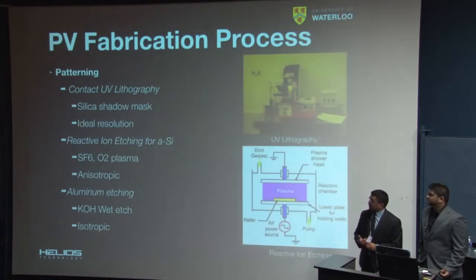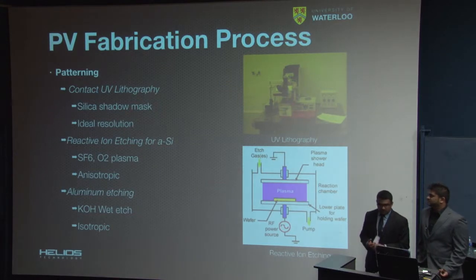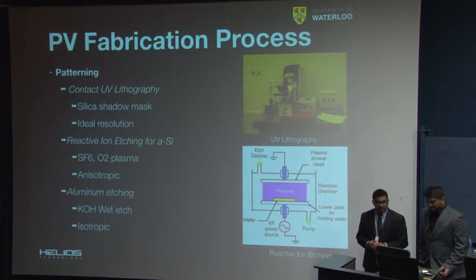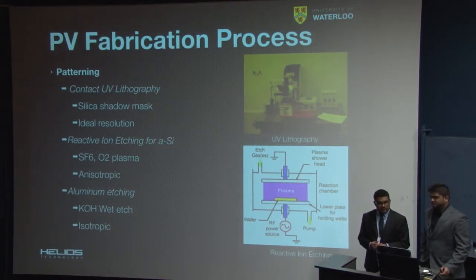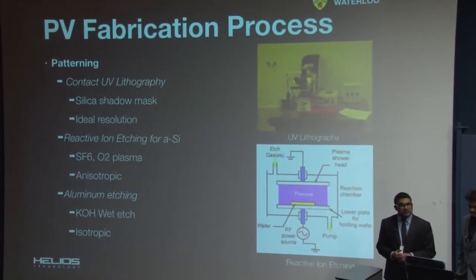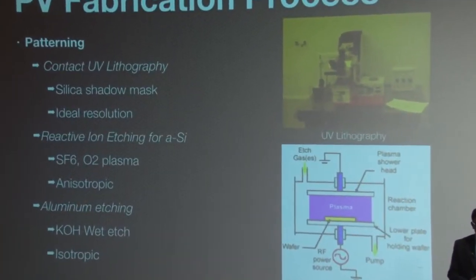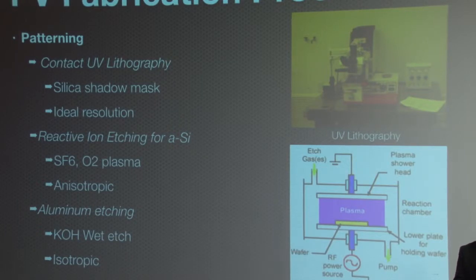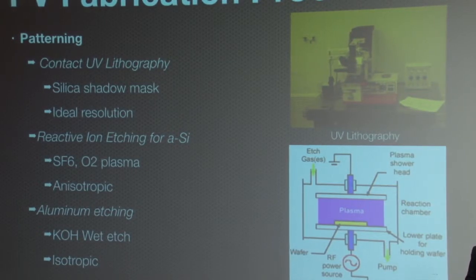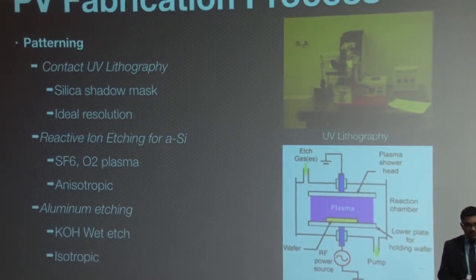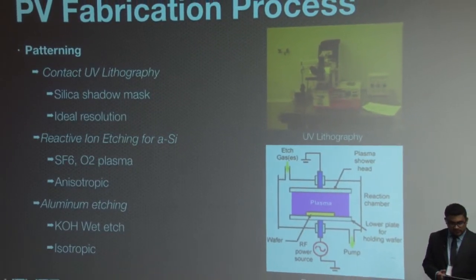We did our patterning using contact lithography with a silica shadow mask. And to etch the amorphous silicon, we used SF6 plasma for reactive ion etching because this provides a good anisotropic etch of the silicon. And we did our aluminum etching through KOH.